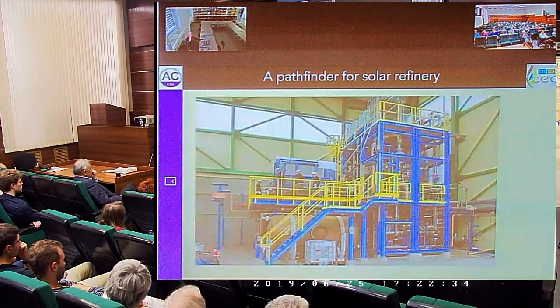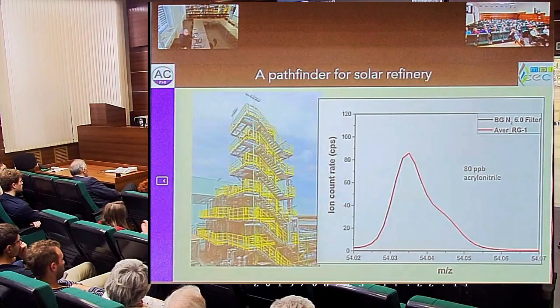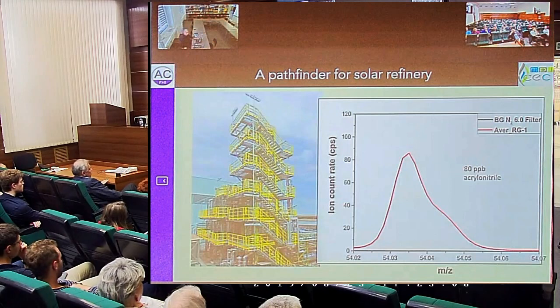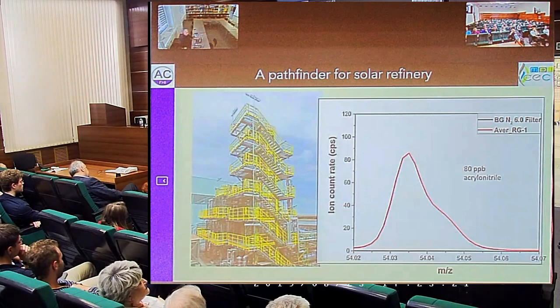That's our gas separation unit that also has already reached a certain size. In here, we practice in particular to remove the trace impurities that are very toxic for downstream catalytic applications. And I give you just one of the challenges that we have with the detection of these impurity gases. You would not expect necessarily that out of a unit where you get 80 ppb of acrylonitrile as a toxic gas that comes from this gas purifier, but in an hour it forms a monolayer of condensed polyacrylonitrile on a copper surface and the catalyst is simply dead. So these are the systems that we have to study very extensively in order to solve this, and this is already an analytical challenge in its own right. We have more than 500 molecules that come in amounts of below 1 ppm out of this machine. So this is still an issue.